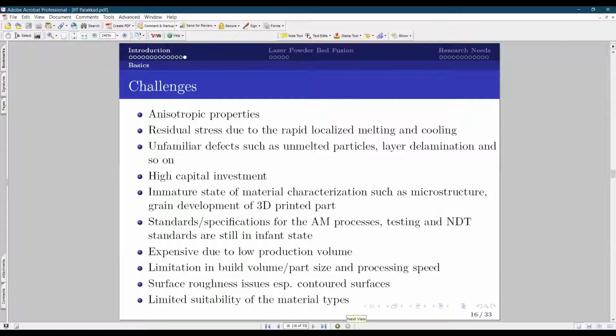For example, Ti-6Al-4V, titanium with 6 aluminum and 4 vanadium, has a heat treatment in the conventional standards. But whether the same heat treatment is applicable to the 3D printed component, we can't say surely that it is the best heat treatment, because your input stock, the 3D printed state material itself, has a different microstructure. When you try to implement the traditional heat treatment, I don't think it is going to get you the similar microstructure that you get in the traditional process.